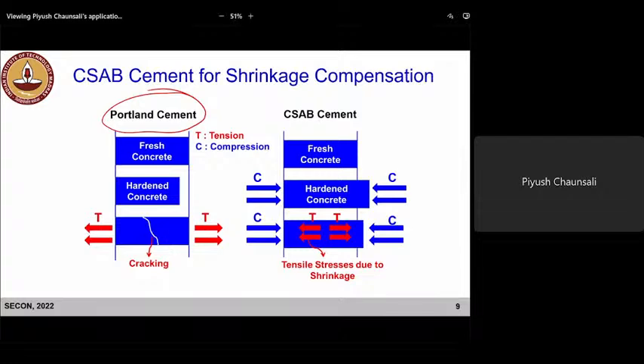And we know that concrete is weak in tension. So what happens when the tension or tensile stresses exceed the tensile strength of concrete? There is a cracking. That's what happens. It's called restrained shrinkage cracking, right? If you take example of pavements, you see transverse cracking. So we would like to reduce the shrinkage normally, right? So there are some admixtures like shrinkage reducing admixtures people use to reduce this shrinkage, because if we are able to reduce this drying shrinkage, we will be able to control this cracking associated with it.